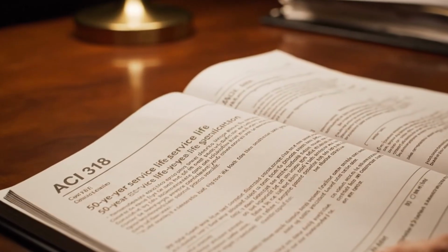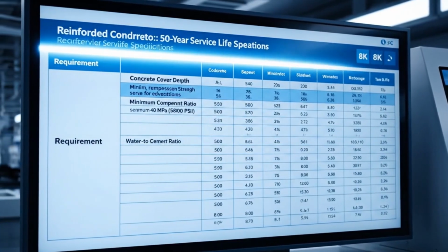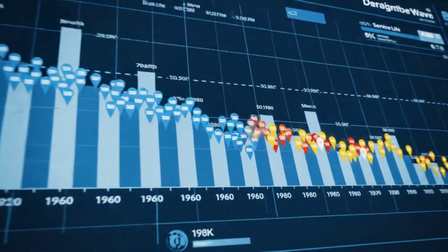Iron reacts with water and oxygen. The oxide occupies 2 to 6 times the volume of the original iron. The concrete cracks, more water enters, more corrosion, more cracking. A self-reinforcing failure loop called the corrosion cracking cycle. It is why reinforced concrete has a finite, predictable, and relatively short service life.